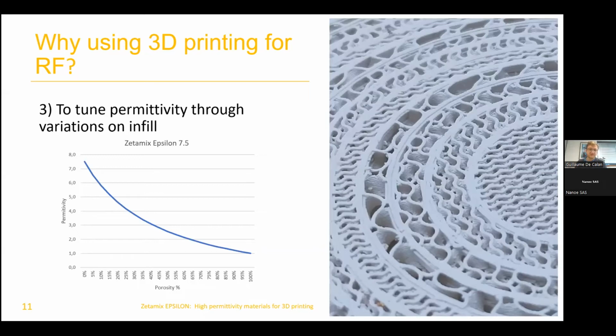Of course, you need to know exactly how the material will behave. There is a law to calculate how much porosity you need if you want a given permittivity. But typically, if you want to be at 5, you can use a 7.5 and print with 15% porosity, and you will actually have a material that has a permittivity of 5. This can be extremely useful.